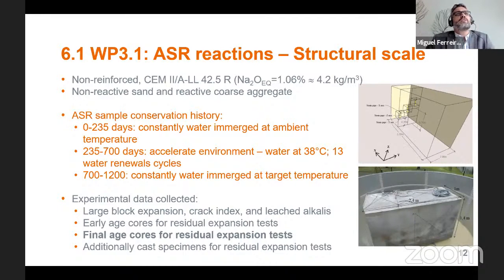So from this experiment, there was also instrumentation. So we were measuring expansion at different heights inside the block and in all directions. And all the sensors were kept, as you can see in the top figure, on 1/3 of the block. So we would have a large part of the block which would be unaffected by cables or any kind of foreign elements inside the concrete.